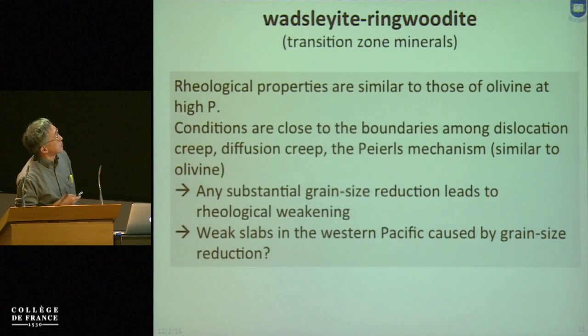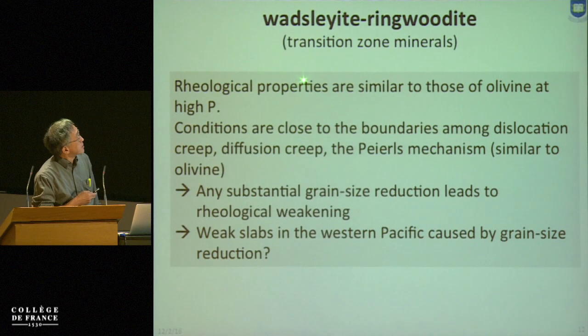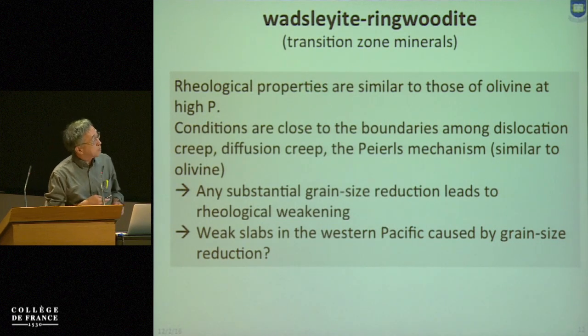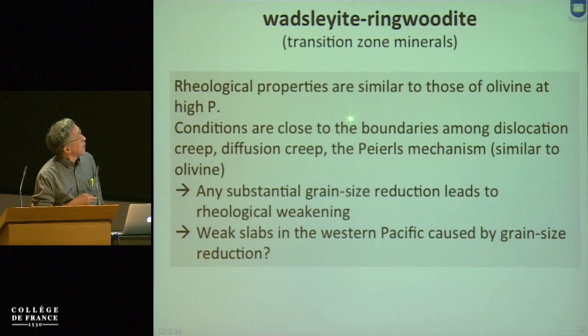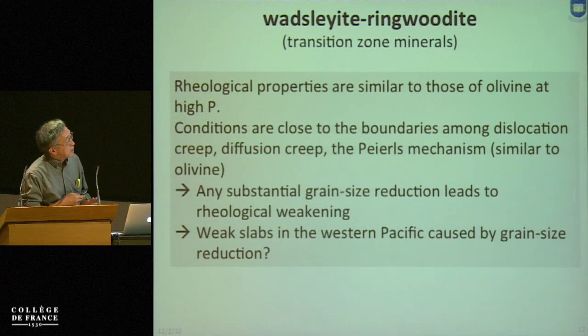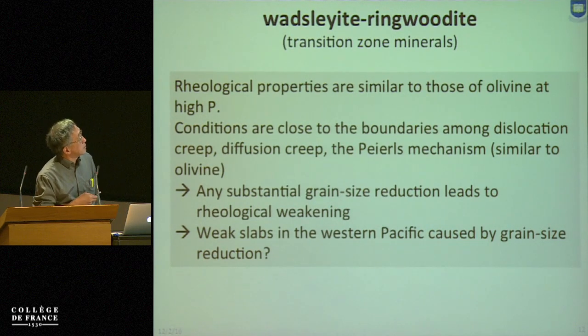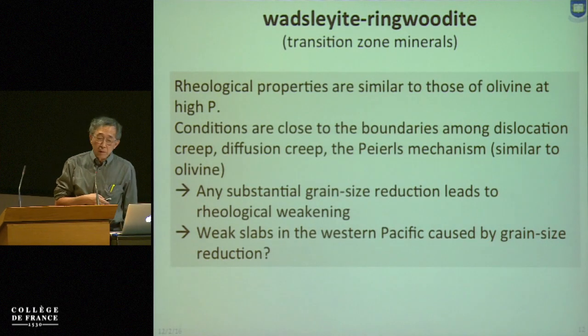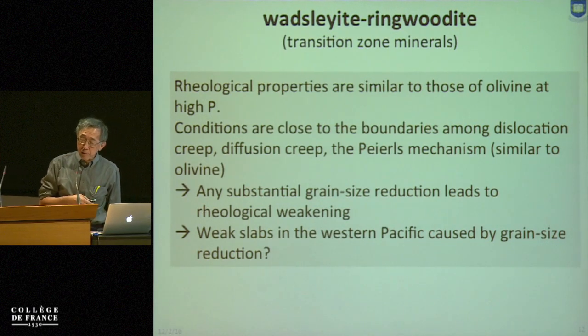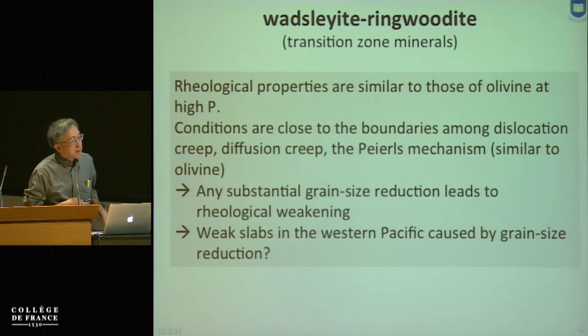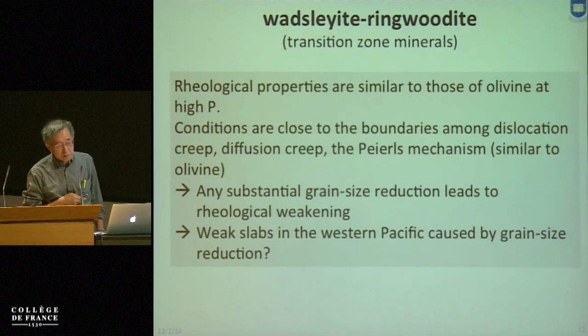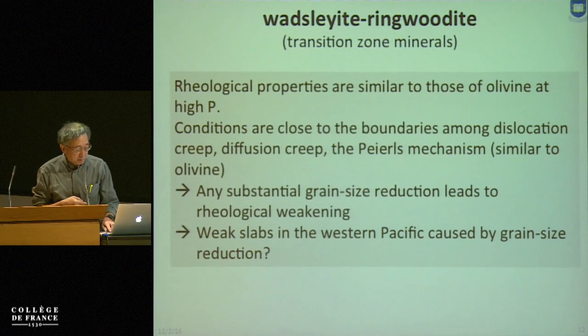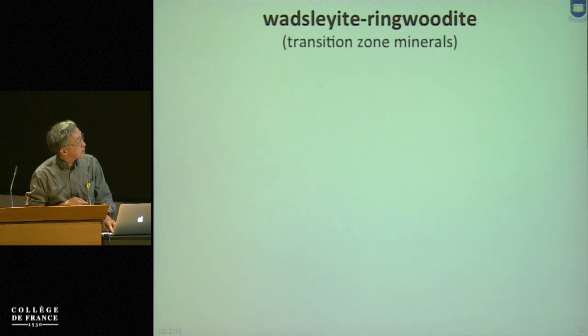So the main conclusions for the transition zone minerals are that when you compare the strength of the transition zone minerals with olivine at similar pressures and temperatures, the strength is not so different. But perhaps the most important conclusion is that the deformation conditions are so close to the boundary between the dislocation and diffusion creep regimes. A very simple implication is that if this is the case, and you have a mechanism of grain size reduction, you could get a very large viscosity reduction. So this is one conclusion that you can get from this analysis.